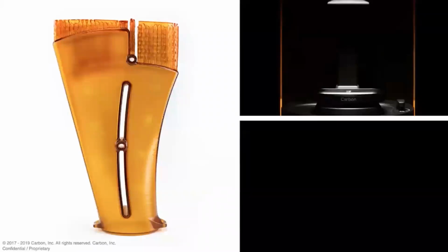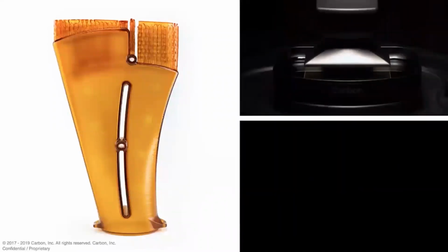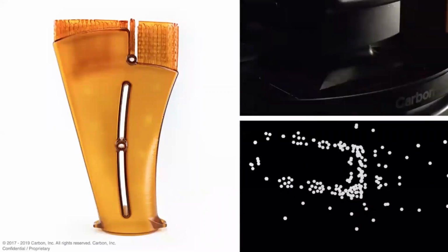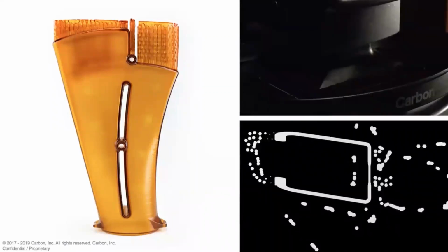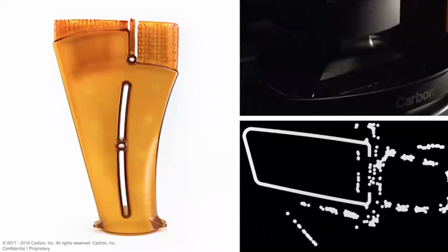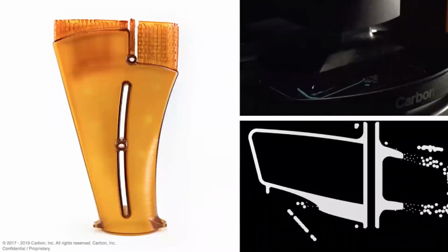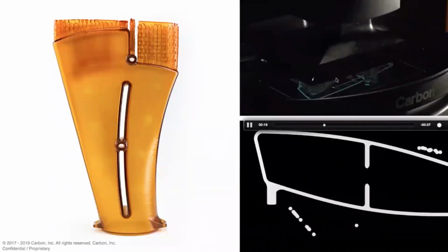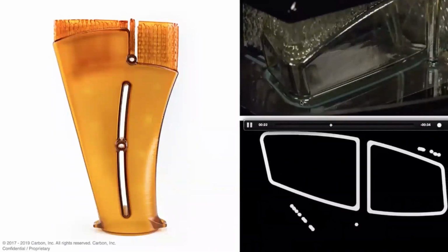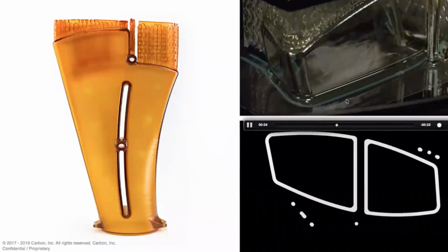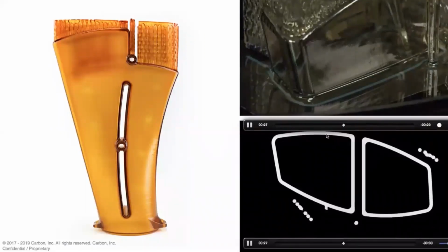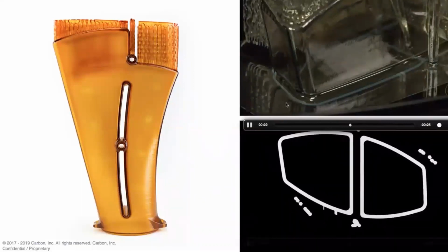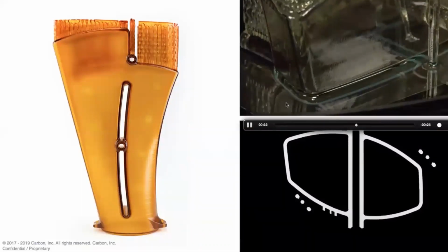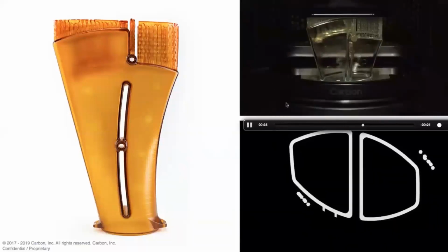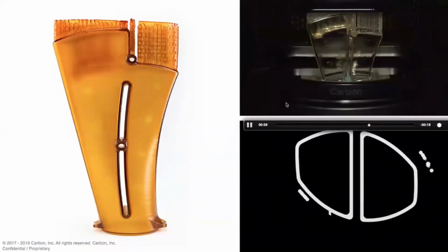This is a platform lowering into a resin reservoir with that very special window at the bottom. We'll get really close to the window, and then you'll see the light turn on. And the light is going through a two-dimensional image as a movie. And the part will bond to the platform shown in black. And as it pulls the part up, it looks like it's really just coming right off the window. But what's happening is that there's a gap right at the window that allows resin to flow in underneath it as you're pulling up the part to make the object that's shown on the left.